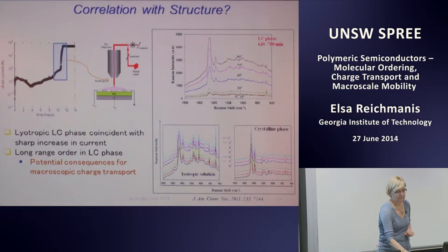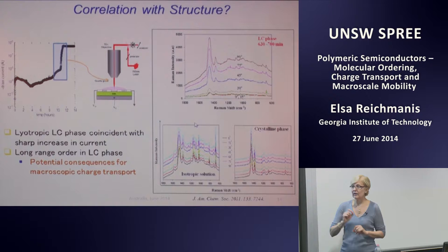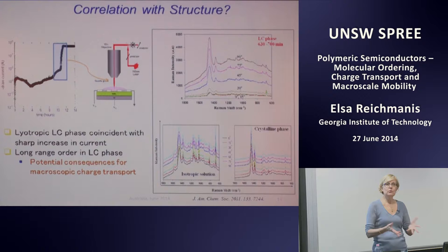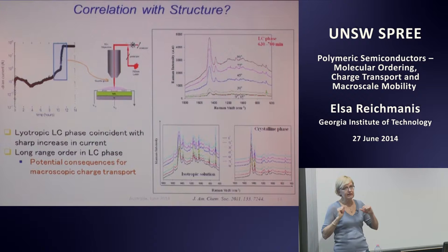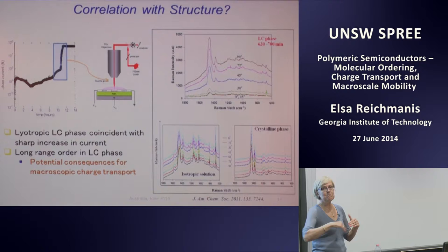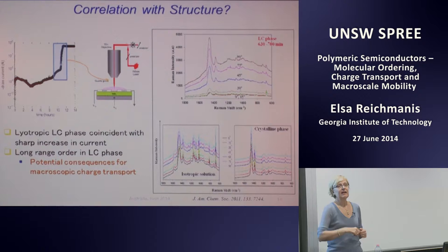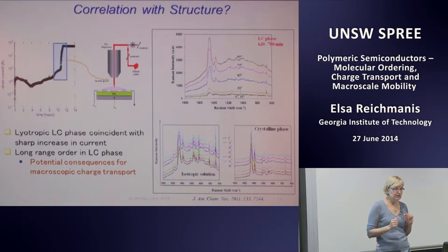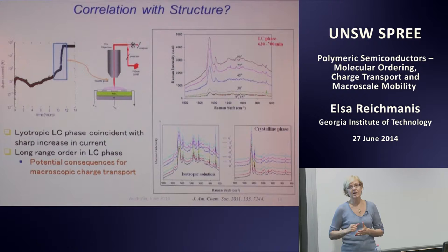The time frame can change depending on conditions in the room during that evaporation process, but the trend is always the same. If we do micro-Raman measurements, in particular polarized optical measurements using Raman spectroscopy, we also see that there's a crystalline phase that forms at some point prior to complete evaporation of the solvent. It appears that this liquid crystalline phase is coincident with a maximum in the mobility that we see as solvent is evaporating. And then when solvent is completely evaporated, the mobility drops a little bit. What we're interested in investigating further is whether we can manipulate order using a liquid crystalline phase in order to optimize macroscopic charge transport through the film.